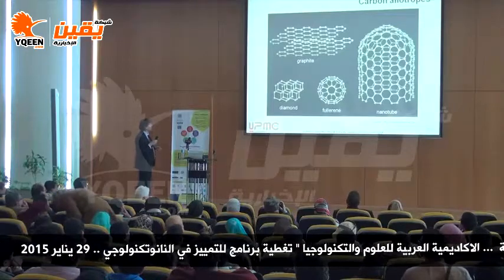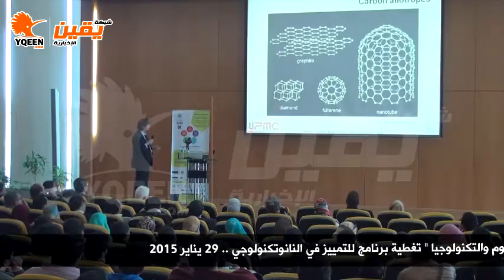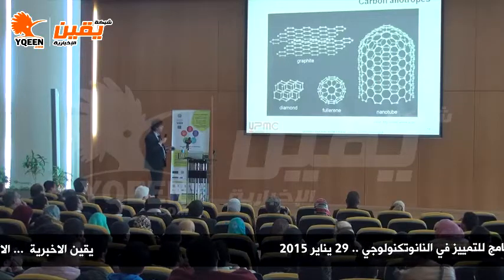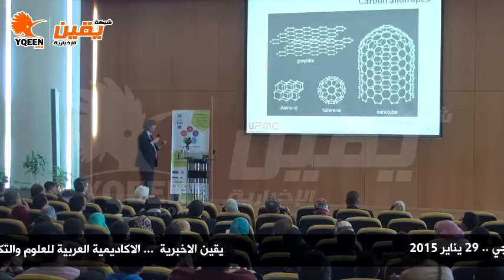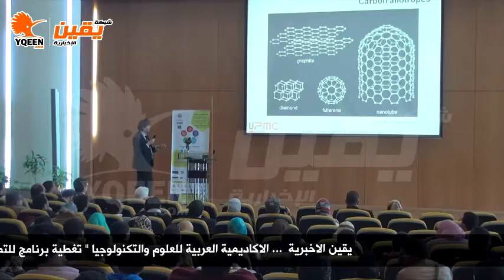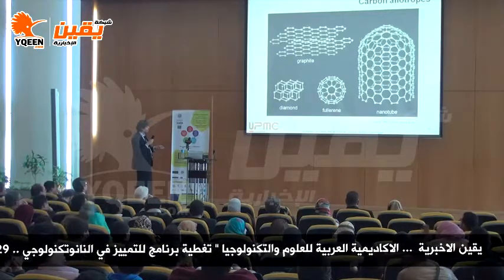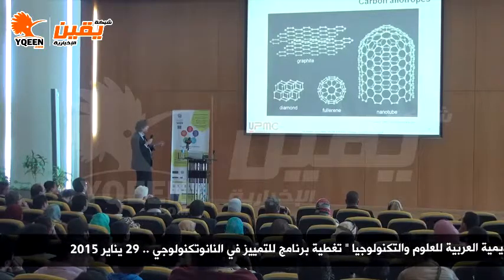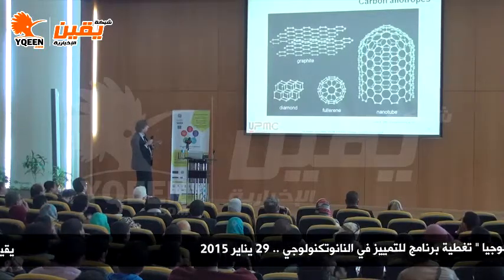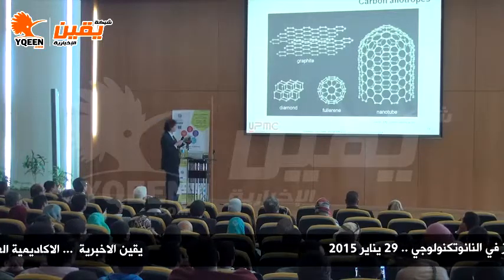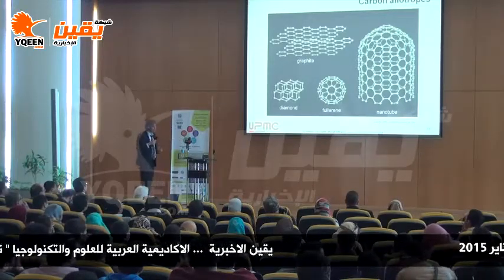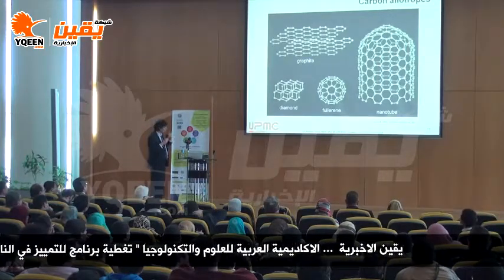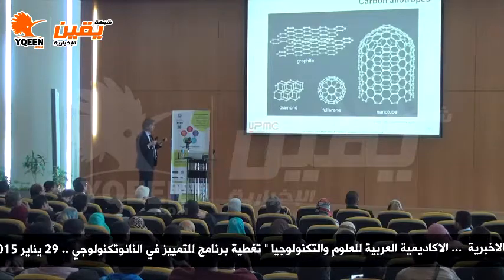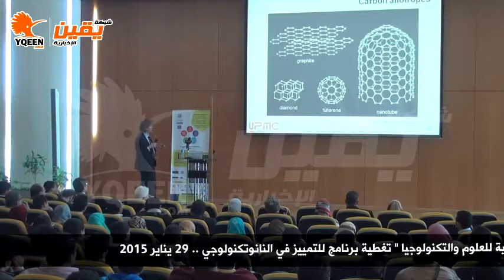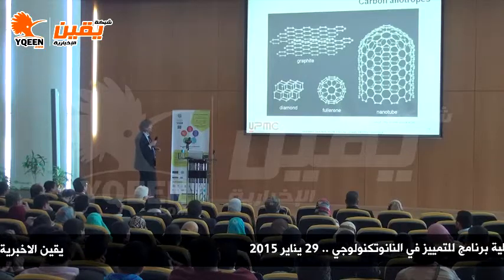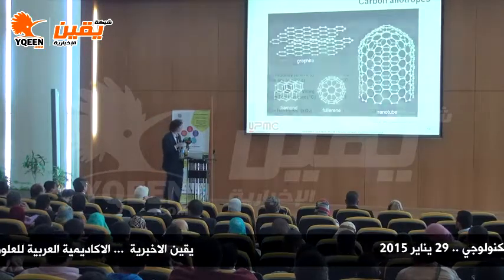Here, a picture of carbon nanotubes, which are more or less based on the same atomic structures, honeycomb structures, but with various configurations. Here, 1D configuration of nanotubes, 0D with the buckyball fullerene, diamond lattice, and a stack of honeycomb structures, which makes graphite. Actually, if you exfoliate one layer of this graphite, we end up with graphene. And we can do the other way around and say that graphene is actually the basic material to reconstruct those various lattices with various properties.